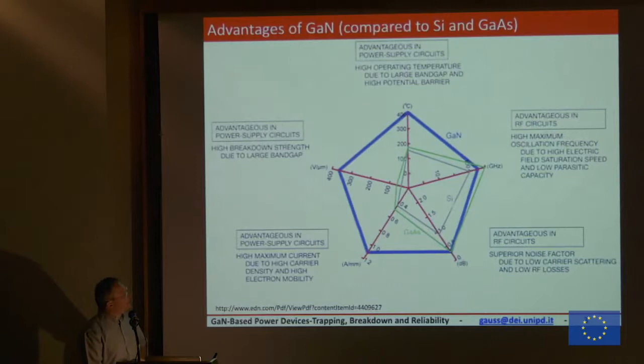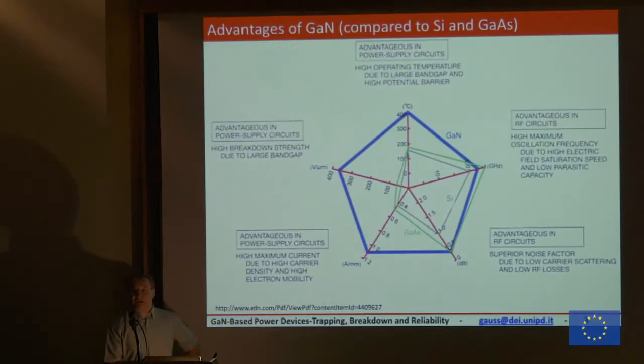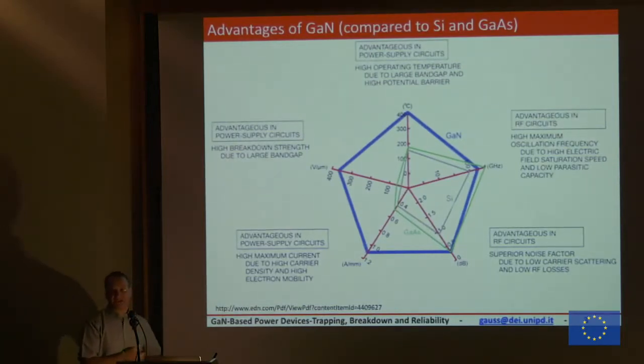You see the big advantages of gallium nitride in terms of maximum operating temperature, because with the wide band gap you have much less generation-recombination. The intrinsic concentration is much lower. We can really go to much higher temperature, so you need much less cooling for this device. So the system is much lighter also, because of the less cooling needed for the operation of the device.